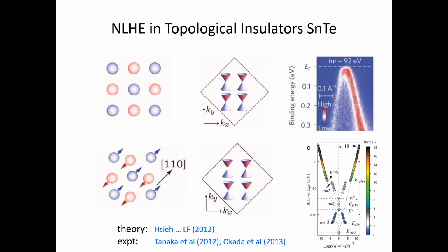So this type of topological crystalline insulator has surface states consisting of Dirac fermions away from high symmetry points in k-space in the surface Brillouin zone. And there are in total four of these Dirac points, because the topological protection comes from crystal symmetry. So if there is a spontaneous crystal structural distortion, for example, if you have a ferroelectric distortion, then the Dirac fermions can acquire a gap. So from massless to massive, okay? So indeed in photoemission experiments and in STM experiments, you can see that a Dirac mass is present. These are experiments from Weidong Luo's group.